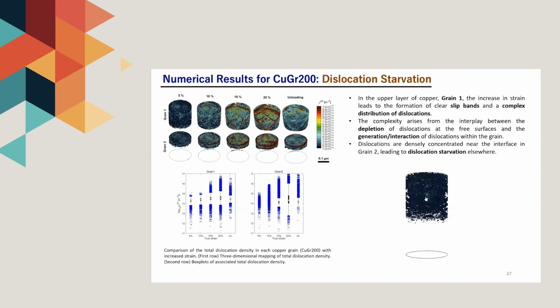More specifically, the slip bands and complex distribution of dislocations are formed in the upper layer of copper, as shown in these figures. The 3D contour mappings indicate the total dislocation density with an increase in compressive strain.